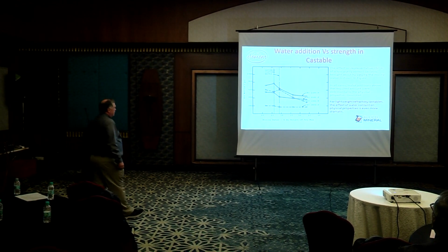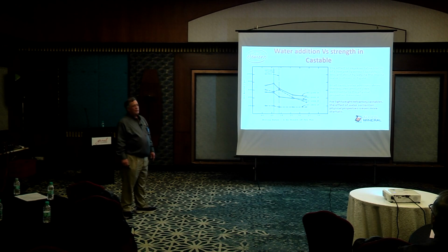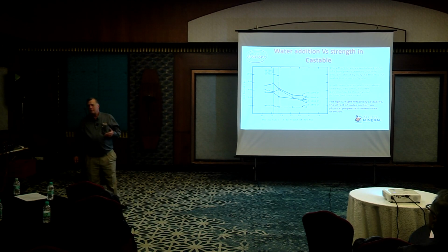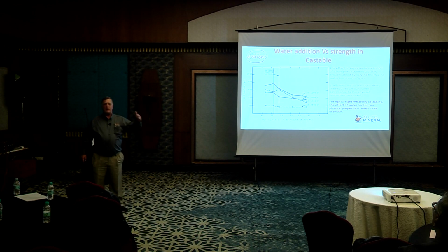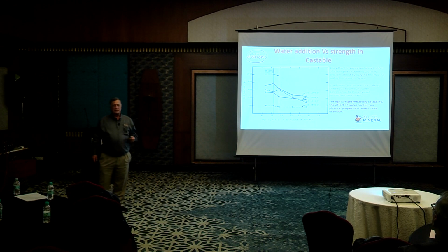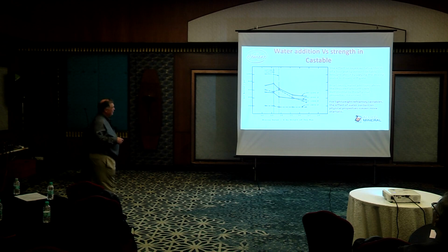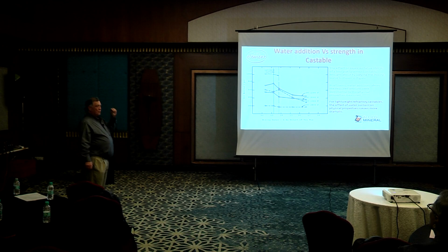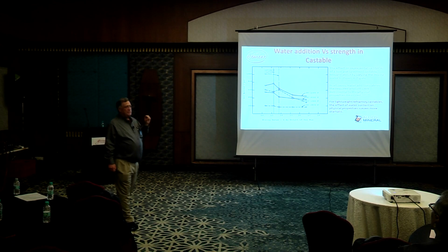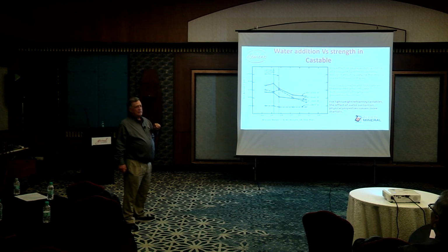So here's what I was saying earlier, when you have to add more water, because now you have to trowel a castable that's supposed to be vibrated at, let's say, 8 to 10% water. Now you need to trowel it, so you're going to add probably more like 10 to 12% water. And what happens is strengths of castables are heavily affected. When they say water range between here and here, that's a very serious point that you need to look at, because we know from testing that if you stray from that, you're not going to get very good hot strength.